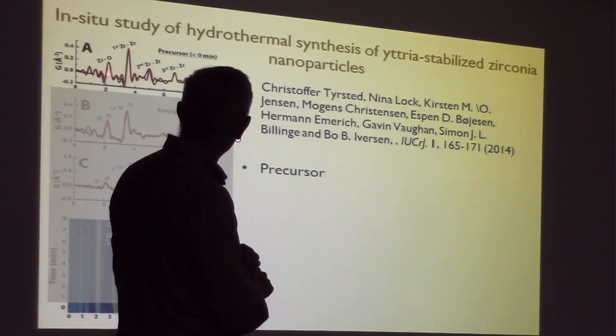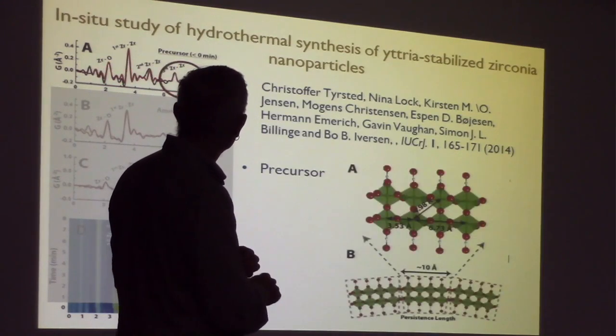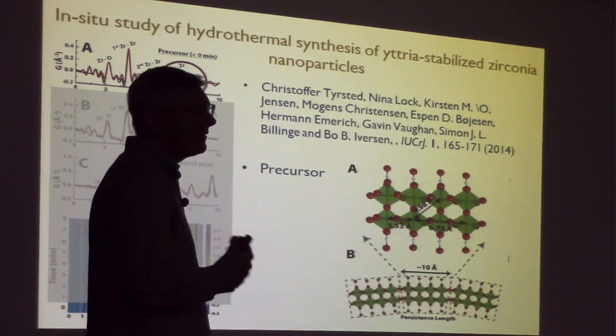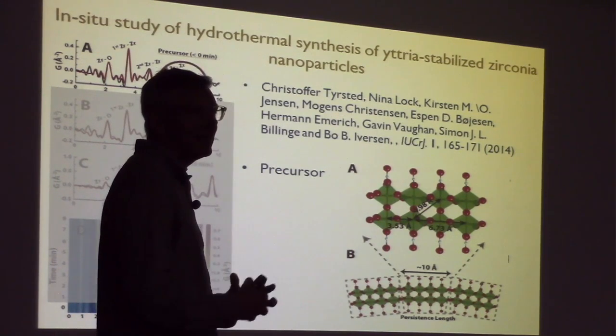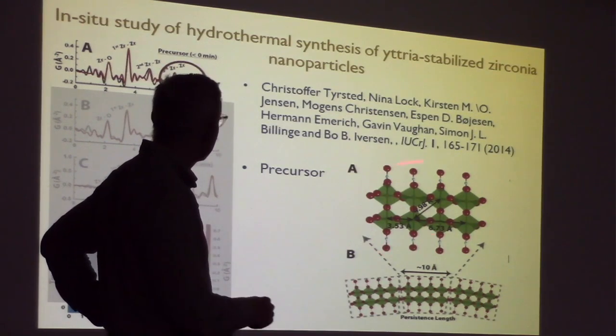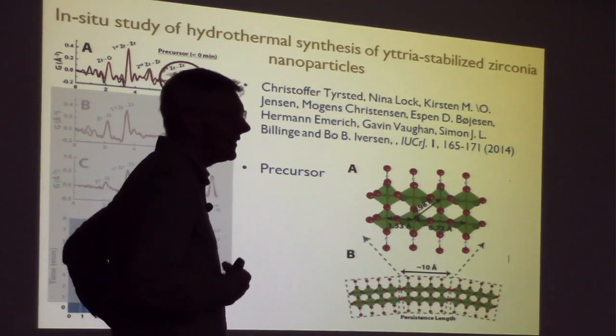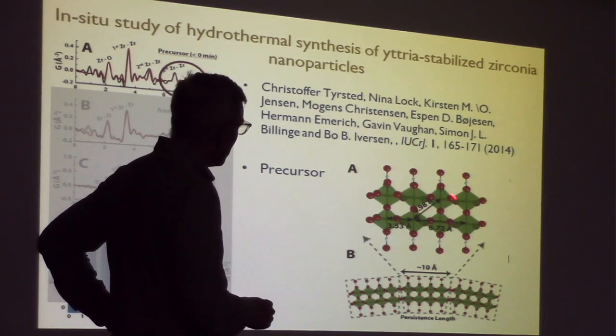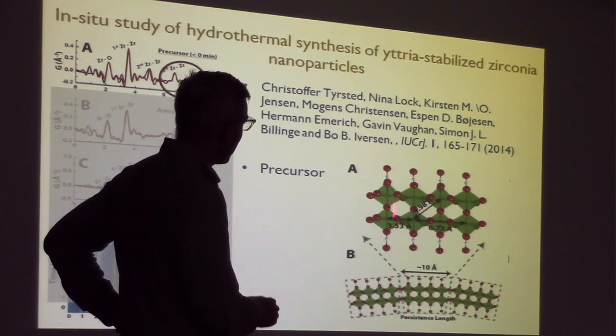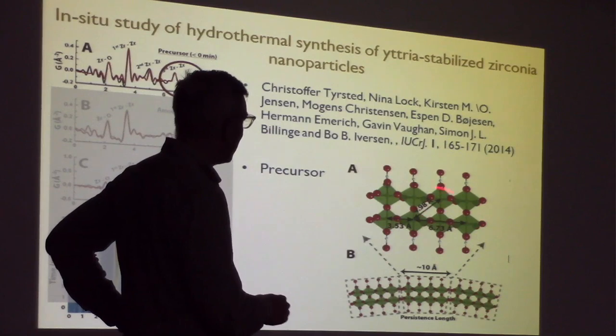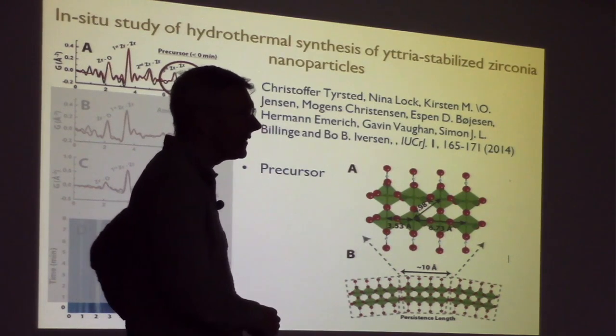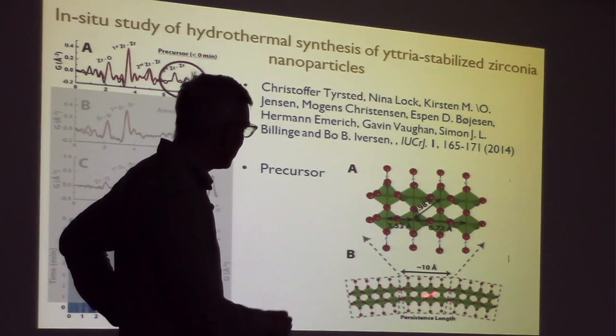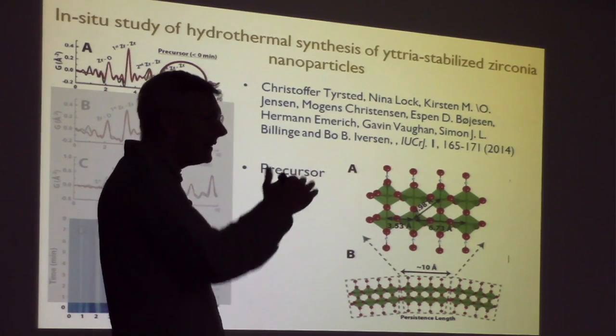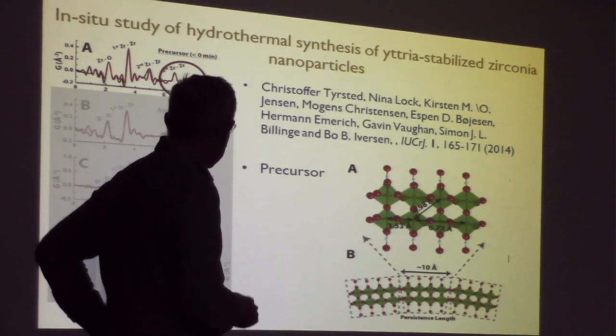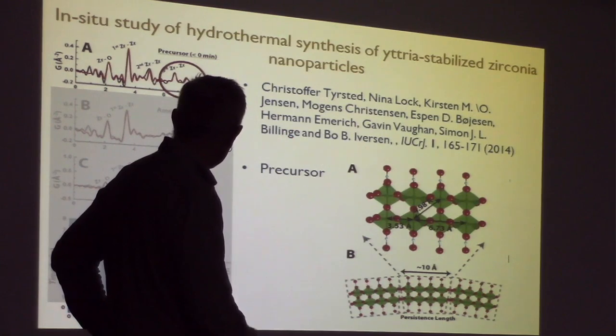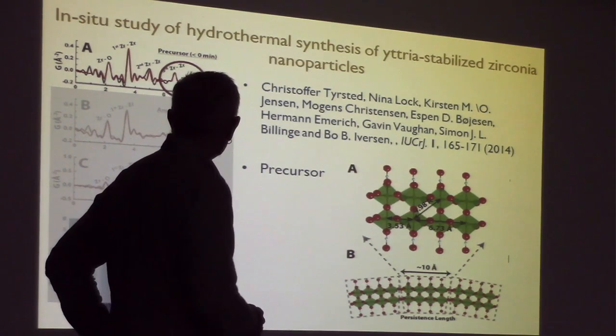What we found here is that we had those peaks that we could see, but we also had these higher peaks. What this means is that the precursor reagent is polymerizing inside the solution. So it's forming something that looks like this. The best fit we could get to the data, this is the work with Kirsten Jensen, who is a former postdoc of mine, was a model where we have these dimers that polymerize into this chain, and they have a kind of 10 angstrom coherence length. We don't actually know if they're clusters this size or whether they're larger objects that are bent, but we can extract this much at least from that. And that's what we see at the very beginning, essentially before the reaction starts.